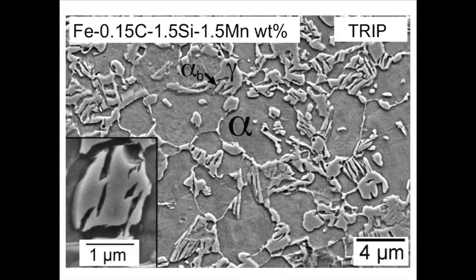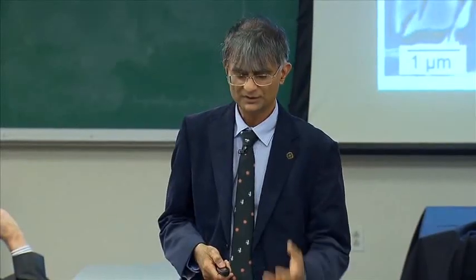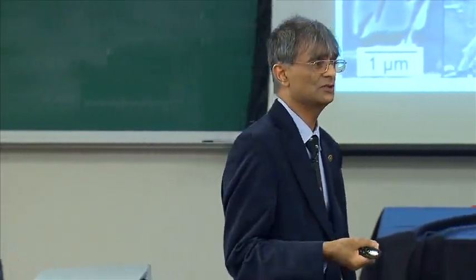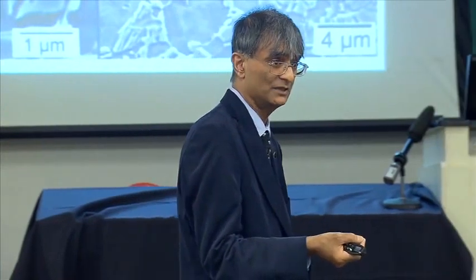But this is a very, very clever alloy in which you produce austenite, which will transform under the influence of stress or strain into martensite, but incredibly cheap, using carbon as an alloying element. Now, you can't use a large carbon concentration because you have to be able to weld these things. There's approximately 3,000 to 5,000 spot welds in every car. Okay? And if those do not pass rigorous tests of fatigue and so forth, your steel will not be used. Simple as that.